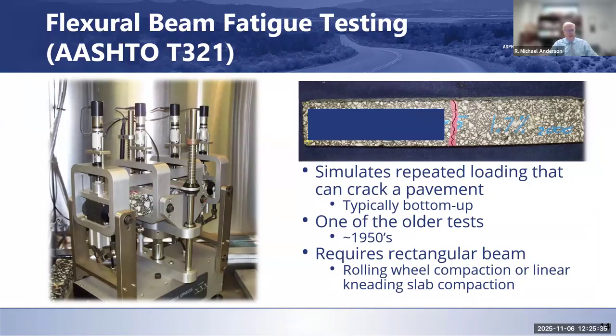This is flexural beam fatigue. So you're creating these beam specimens overall. They get loaded in the fixture that you see there. It's 4-point bending. This was discussed in the literature in the 1950s by Professor Monismith and Dr. John Epps, intended to simulate repeated loading that you would see in a pavement that would get cracking, typically bottom-up cracking overall. On the left is the apparatus. The beam is 63 millimeters wide, 380 millimeters long, 50 millimeters thick. The inner 2 clamps move relative to the outer 2. So the outer 2 fix it in place, the inner 2 move back and forth, at whatever applied strain you're putting on it.